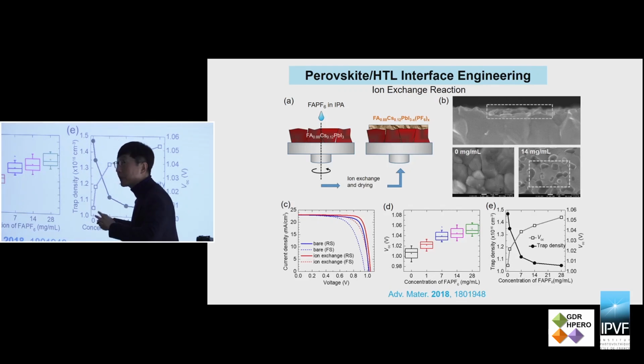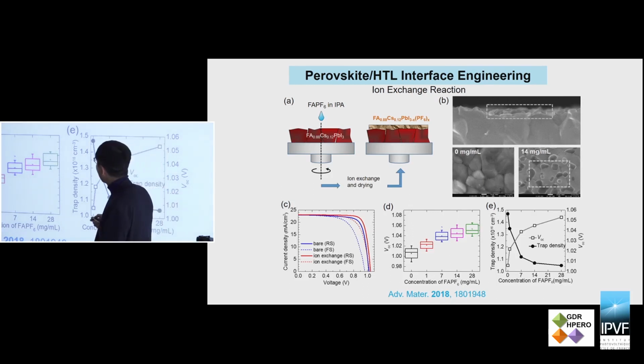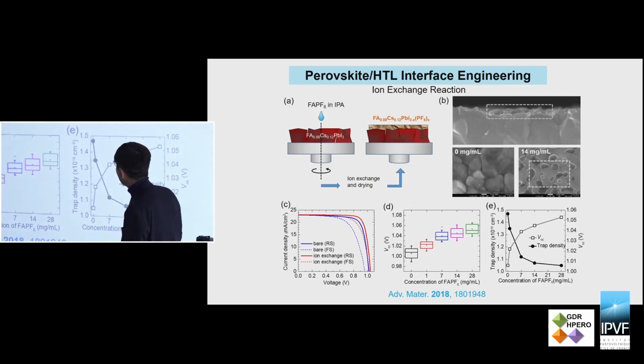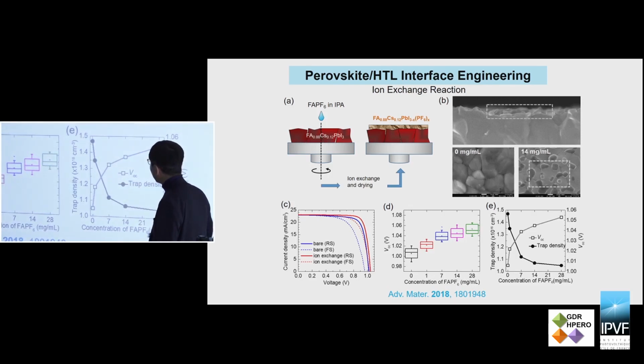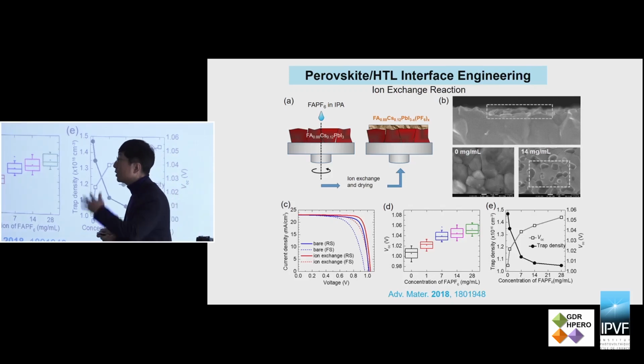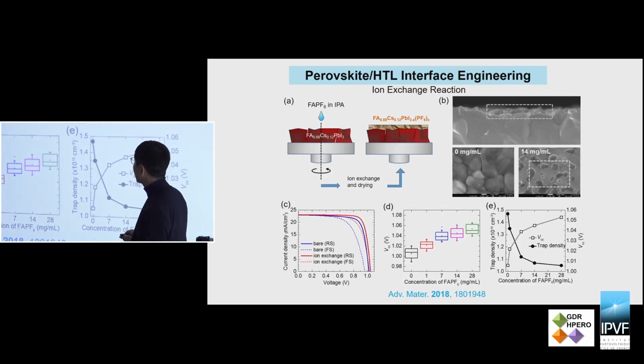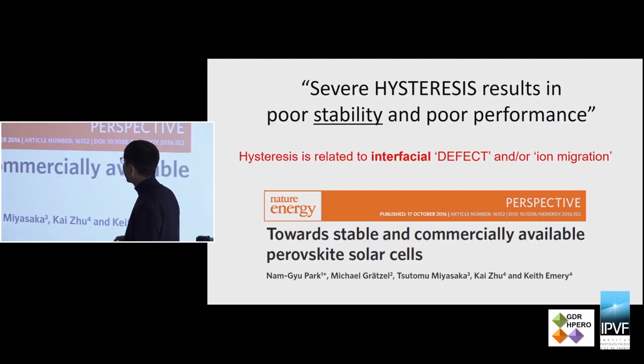Therefore, we would like to exchange some anion by using some PF6 anion, and then we introduce a second phase of the perovskite layer having a different anion. By doing this, we can see increased open circuit voltage and fill factor, and also decreased trap density. So this is an interfacial engineering approach. I gave you some examples. There are so many reports regarding interfacial engineering.